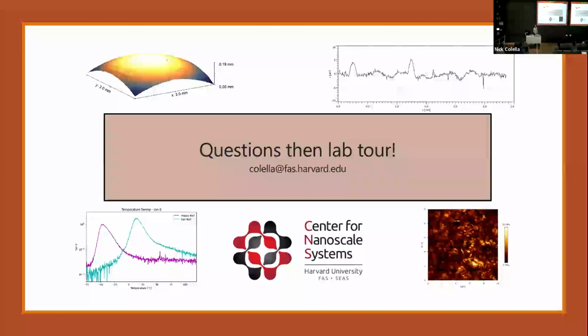So depending on the conductivity of that underlayer, we could probably still do DSC because, assuming that that layer is not doing anything by heating up to 220, we would just heat up the whole system and you would still get a DSC trace. Your exact enthalpy values, which we calculate in joules per gram, would not be quite accurate unless we can recalculate how much of the material was the polymer, but we can still see where the transitions occur. The temperature is going to be accurate. It's just the enthalpy of melting would not be accurate for a crystalline. But yeah, DSC, and again, the DSC pans are about 5 millimeters in diameter, so we would need to have a 5 millimeter circle sample to be able to put it into the DSC.